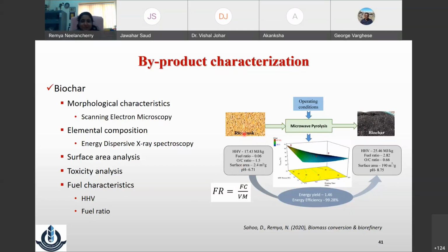So here you can see the property of rice husk. Prior to pyrolysis, it has a very low heating value. Fuel ratio, that is fixed carbon content to volatile matter content, was much less. And the next property is the O/C ratio. Oxygen to carbon ratio was high, around 1.5. Very small surface area. The rice husk as such has low surface area only, and the pH was near neutral, around 6.71.